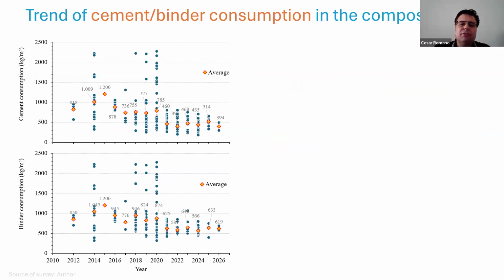I prepared for this presentation a survey in which I evaluated many papers from the literature, collected from 2012 to 2026, and organized the results on cement consumption and binder consumption in 3D printing concrete reported in the international literature. I considered more than 200 compositions. It's clear that between 2012 and 2020, most formulations were characterized by very high cement and total binder content, because during this period buildability had priority. This resulted in high cement and binder contents, exceeding 800 kilograms per cubic meter.